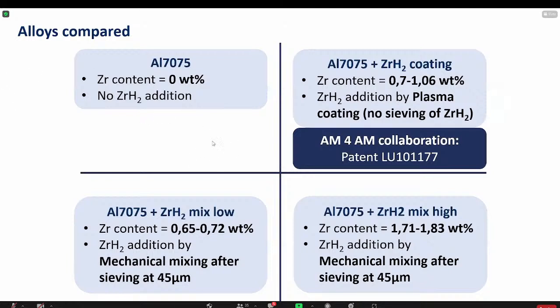I have compared 4 different powders during my presentation. I have compared the classical aluminum 7075 without any addition, which is an alloy highly susceptible to hot cracking during the process. And I have compared it with 2 different powder mixes: aluminum 7075 with zirconium hydrides added by mechanical mixing, where the difference between the second and third powder is the amount of zirconium added, one with a low amount and the other with a higher amount.